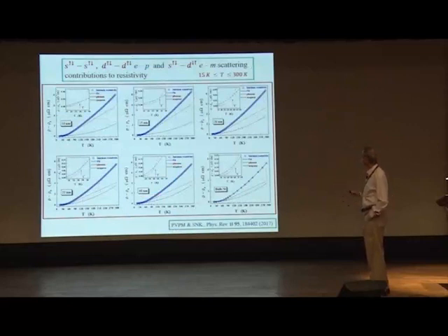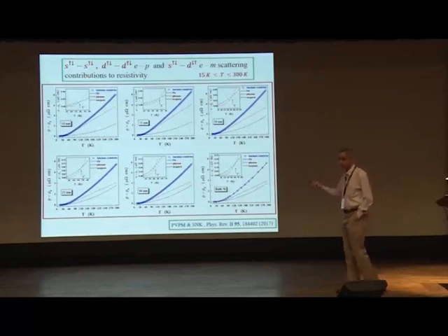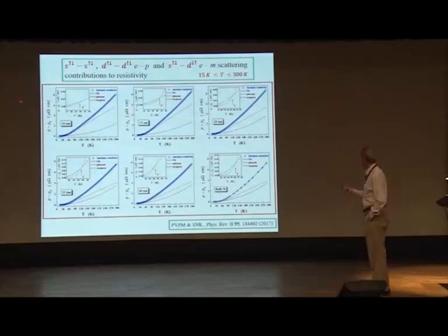Sorry, first I will show you these fits so that you can appreciate the different contributions, how they behave with temperature, and in what temperature range which one becomes more dominant. For example, take any of these. When the crystallite size is low, the major contribution is coming from the electron-phonon scattering.